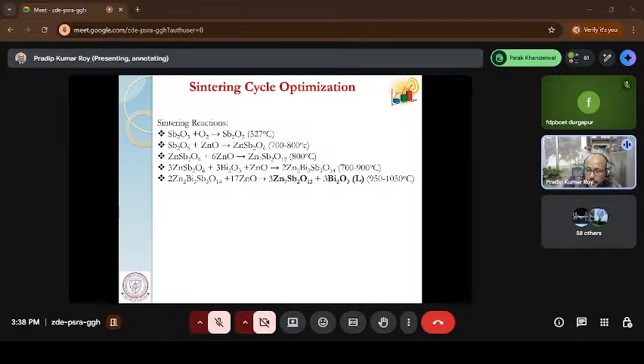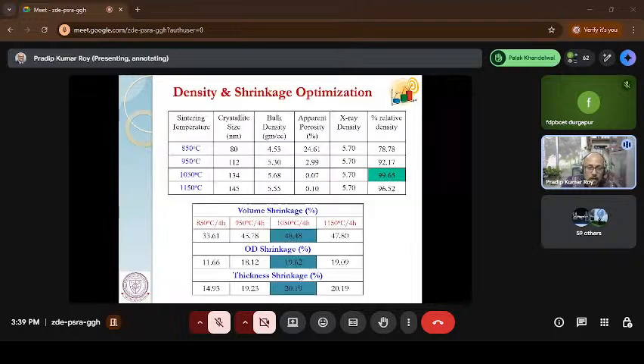Now this spinel phase actually controls the grain morphology of the zinc oxide, it basically acts as a suppressor. It doesn't allow the grain size to increase as well. So it reduces the grain size. Reduced grain size means your number of grain boundaries increases. If the number of grain boundaries increases, you need more voltage to break each grain boundary. That means the rating of the block is also increasing. So based on that, we optimized all the other parameters as well, like the sintering part, and what relative density we are getting from there.